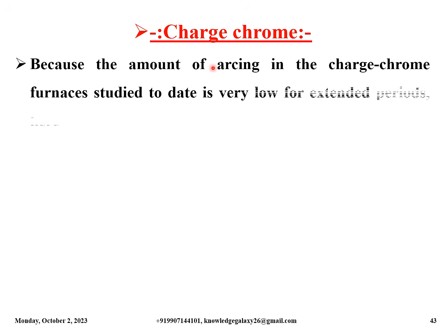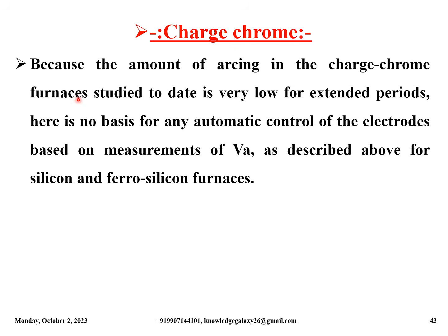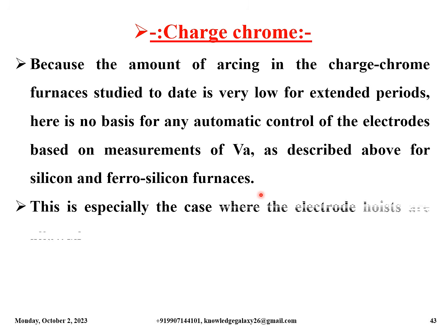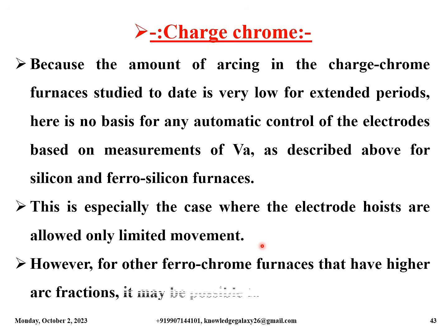Now let us discuss the effects on charge chrome furnaces. Because the amount of arcing in the charge-chrome furnaces studied to date is very low for extended periods, there is no basis for any automatic control of the electrodes based on measurements of VA as described above for silicon and ferrosilicon furnaces. This is especially the case where the electrode hoists are allowed only limited movement. However, for other ferrochrome furnaces that have higher arc fractions, it may be possible to do such control.